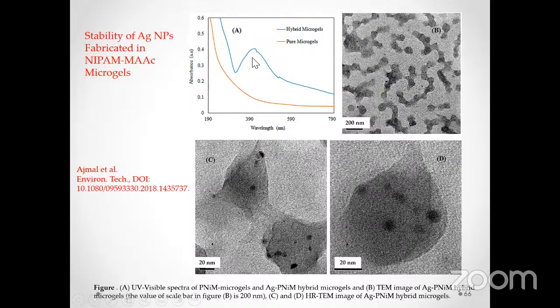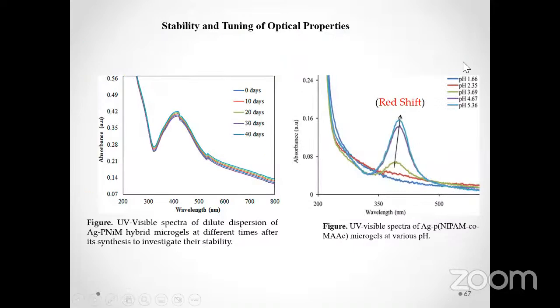And it shows that the system can be used as an optical sensor because it has optical properties. And in this case, again, a red shift was observed when the pH of the system was increased. It shows that hydrogels can be effectively used for the synthesis of highly stable optical sensors. That stability can be observed from this figure, which shows that even after 40 days, the optical sensitivity of the system is not affected by the atmosphere.